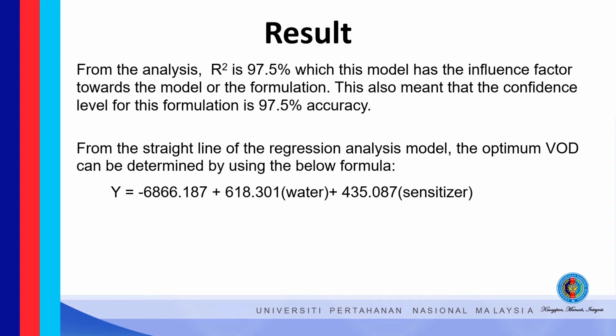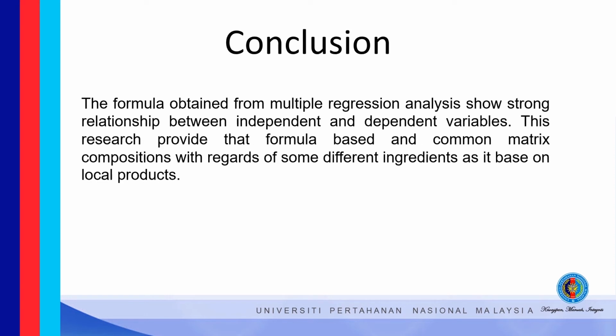From the straight line of the regression analysis model, the optimal VOD can be determined by using the formula below. Y, the VOD, equals minus 6866.187 plus 618.301 times water plus 435.087 times sensitizer. The conclusion: the formula obtained from multiple regression analysis shows a strong relationship between independent and dependent variables. This research provides a formula based on common matrix composition with regard to some different ingredients, as it is based on local products.